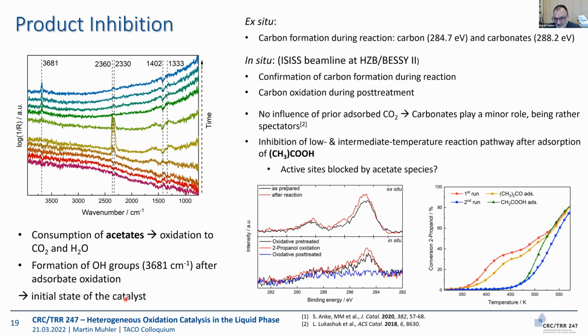These acetates can then easily be oxidized to CO2 and water, then you regenerate the initial state of the catalyst. We did some more spectroscopy with the help of the Fritz Haber Institute, even in situ, and we got there the impression that the carbonates just play a minor role, but it's really this acetate species that is key to understand coking. And now the straightforward experiment is that you do a pre-adsorption experiment. When you pre-adsorb acetone, that is this curve here, then you see very little changes. It's like the conventional low temperature, high temperature experiment. But when you pre-adsorb acetic acid, taking liquid acetic acid, purify it, attach it to your setup, bubble carrier gas through, and then heat up, then you see immediately the low temperature channel is fully blocked.